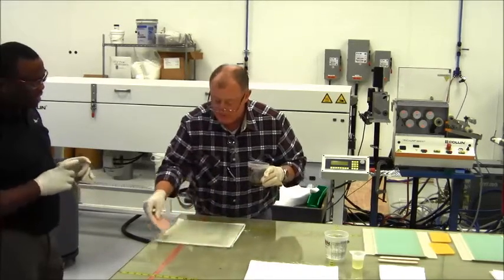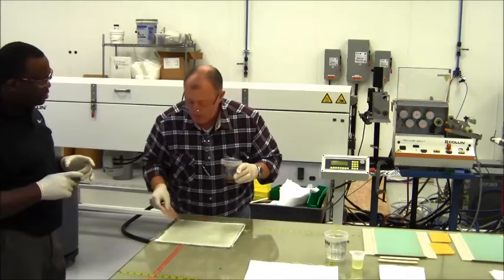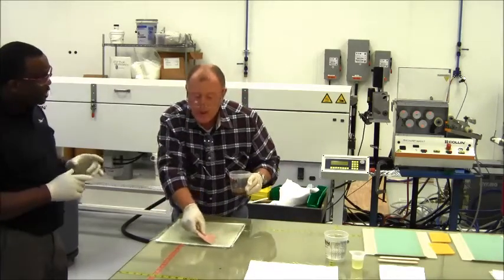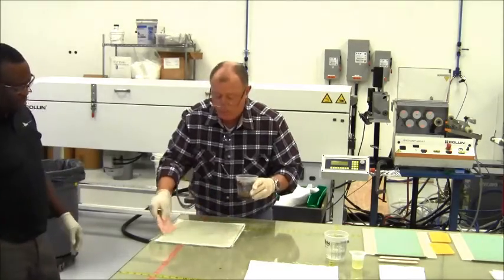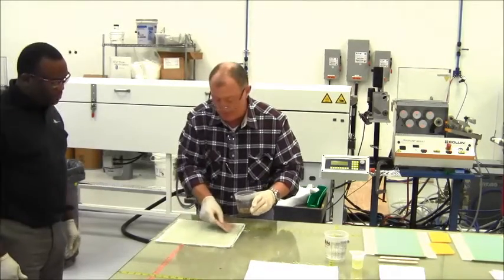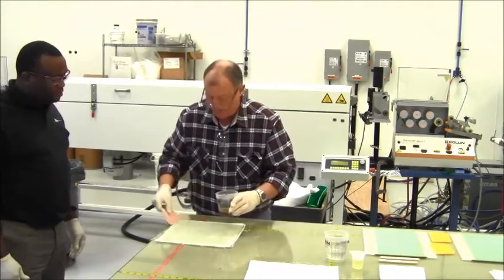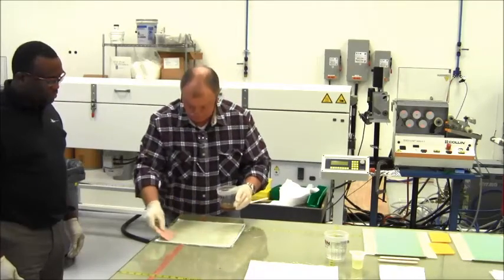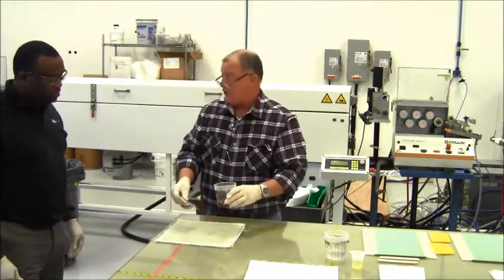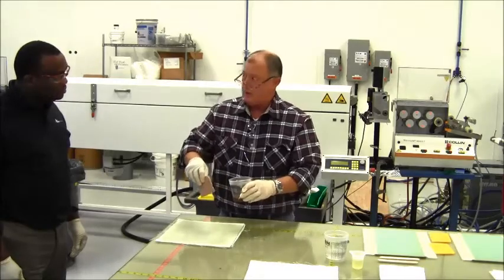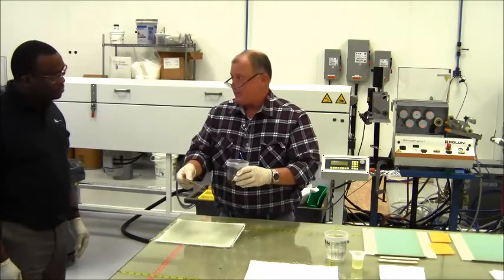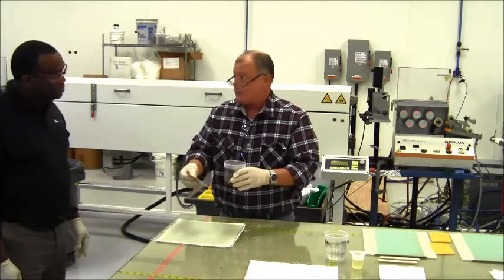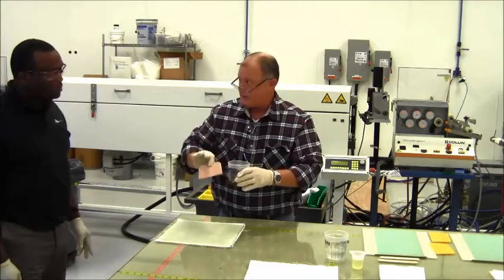So the volume is calculated off the sample size of Innegra. Right. For example, when you do other types of laminates and you use a peel ply, or you're going to do an infusion and you use a flow media, you would have to calculate the volume of each of those materials as well. Obviously, the plastic green flow doesn't absorb any resin, so it's a volume of resin that you calculate. Okay.